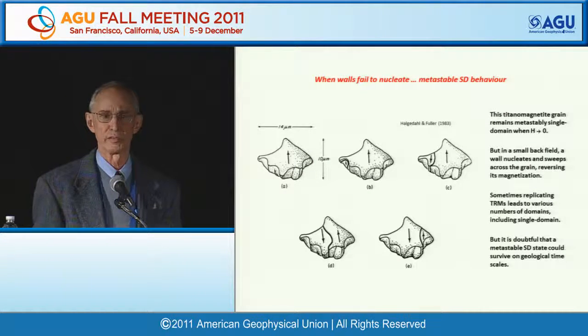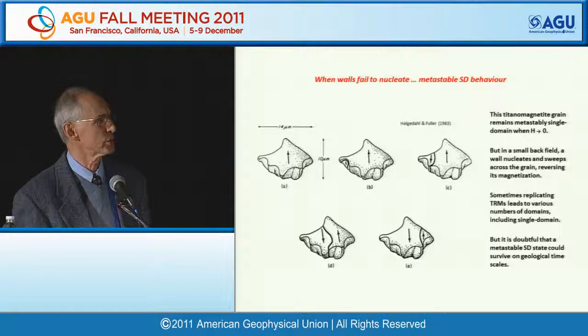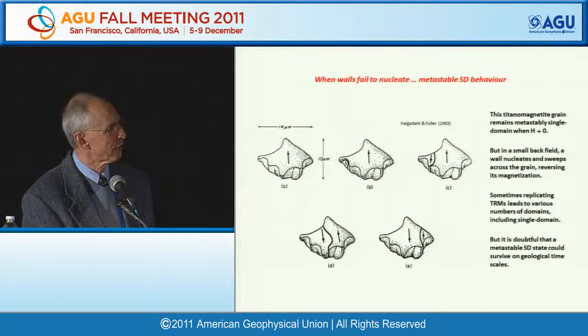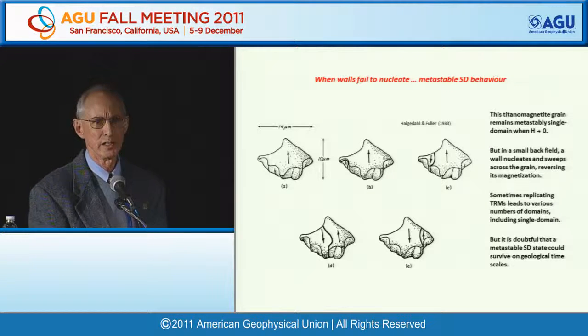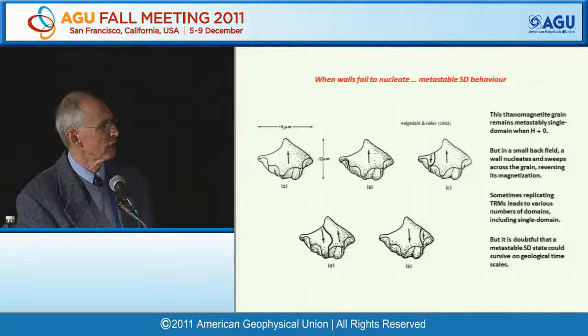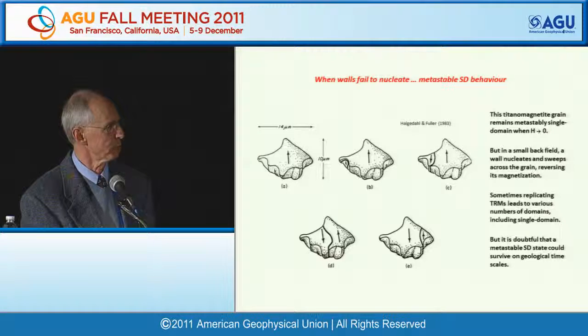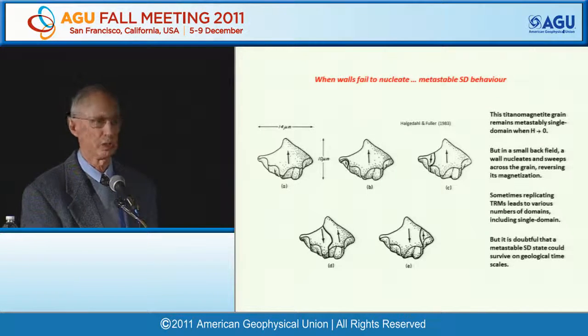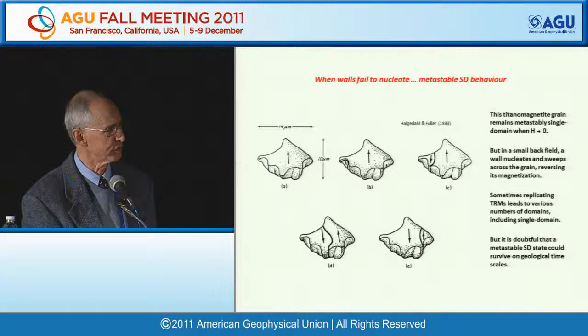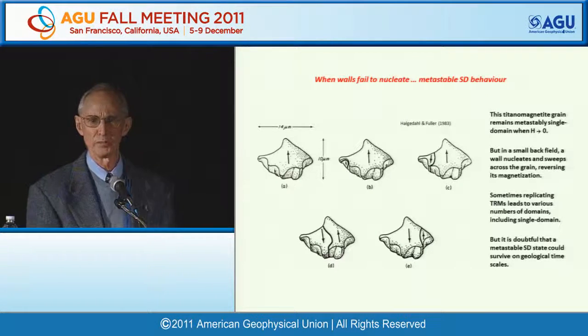Maybe it's the complexity of the real world, the real magnetites, that produces single domain-like behavior. Another very clever idea, when domains fail to nucleate for whatever reason, we can get single domain behavior metastably. Halgedahl and Fuller's original diagram here of a quite large titanomagnetite grain shows something that is single domain. It's been saturated in a strong field, but it doesn't remain single domain for long. If you put a small reverse field in, here's a domain nucleating, and then the wall sweeps rapidly across the particle and reverses the moment.